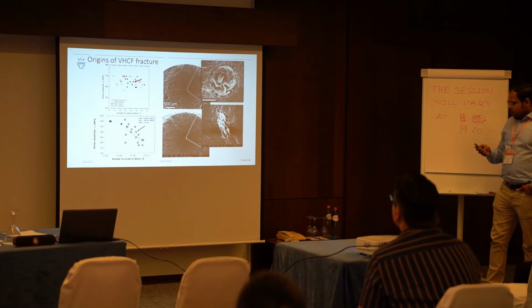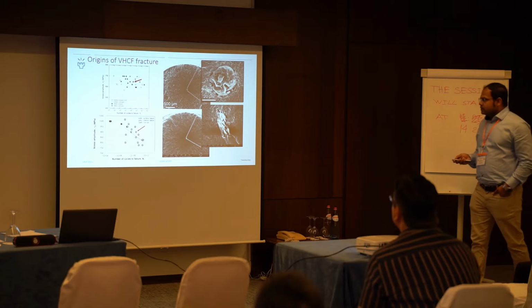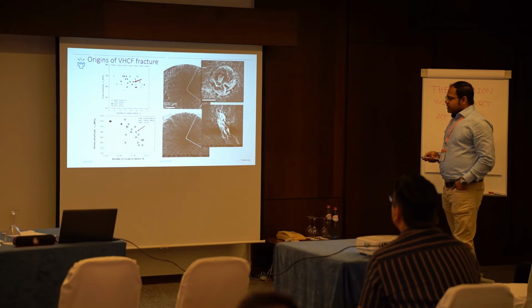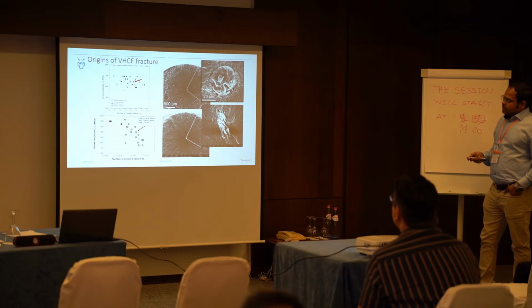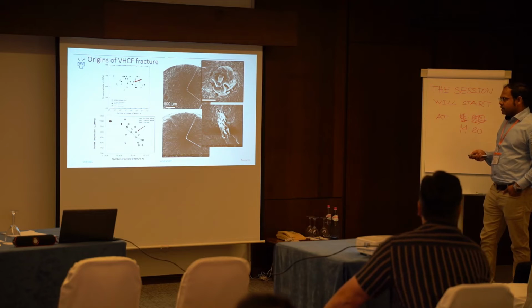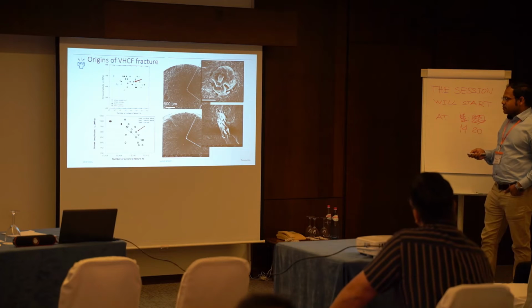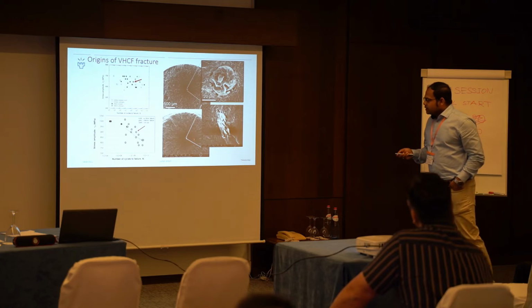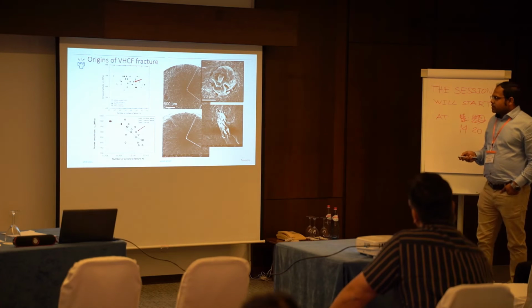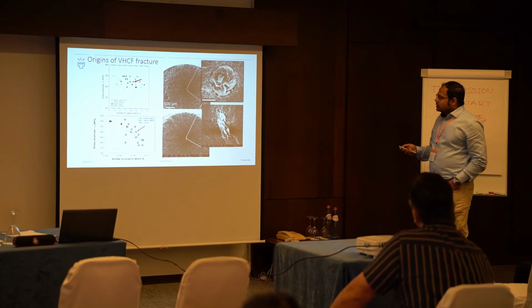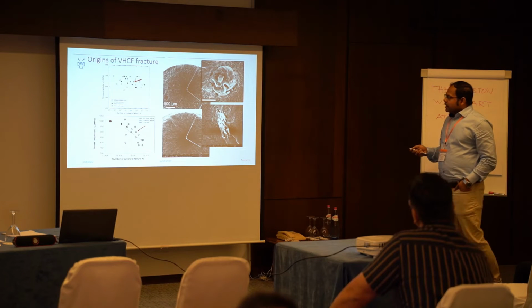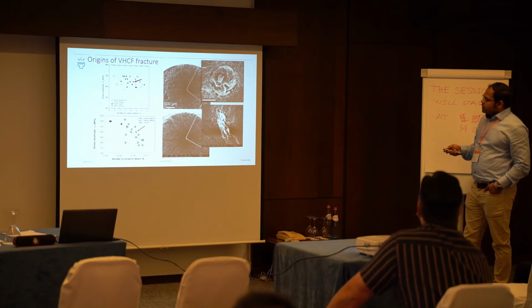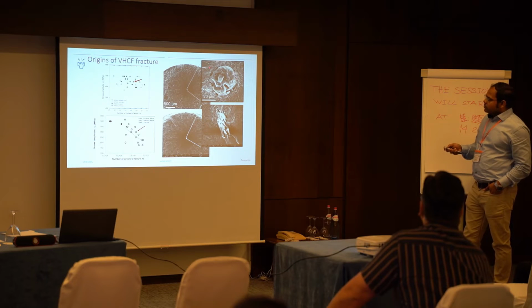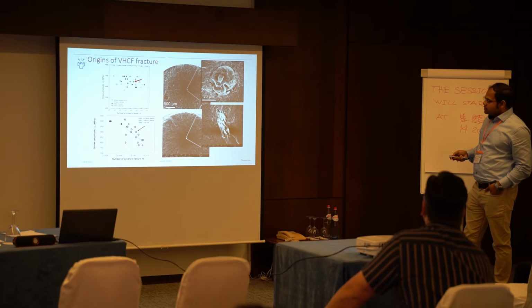Now, when we check the failure mechanism, in both conditions we found that the materials failed from an interior inclusion. In this condition, the DQ&P variant steel, we assumed that this steel may not have a significant amount of inclusion. Still, we see that these materials also failed from a very tiny interior inclusion. Another thing we observed is that near this inclusion, there is a fine granular bright area present, both in this condition and in this condition.